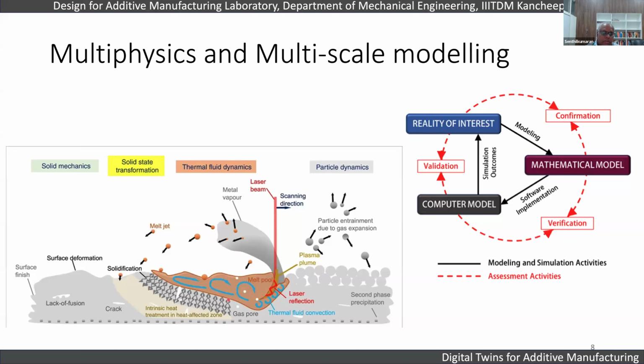Marangoni flow. So Marangoni convective flow draws the powder inside and moves it due to the Marangoni convection. Here also the movement is like this. So you can see the powders are drawn into the melt pool. And you have some vapors being produced, some spattering also occurs with the melt jets moving here and there. So you can see it's complex thermal fluid dynamics happening here at the exact intersection.